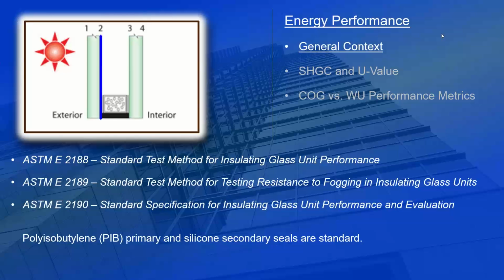Several ASTMs provide test guidance and test methods for IGU performance, for fogging, and insulating glass performances and evaluations. PIB primary and silicone secondary seals are standard. The PIB goes between the spacer and the glass, and the silicone, which has more structural capability, connects the glass to the glass, bypassing the PIB spacer.